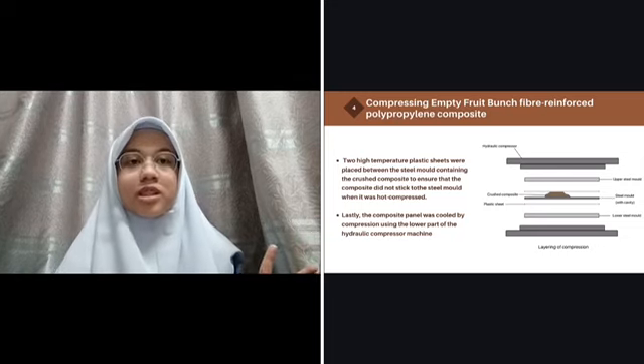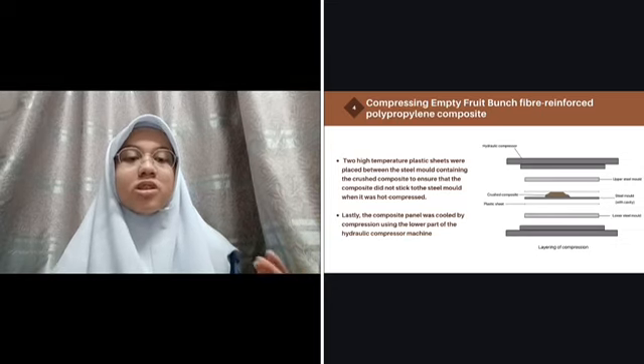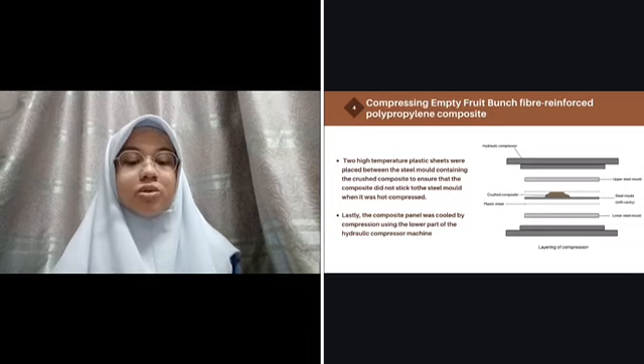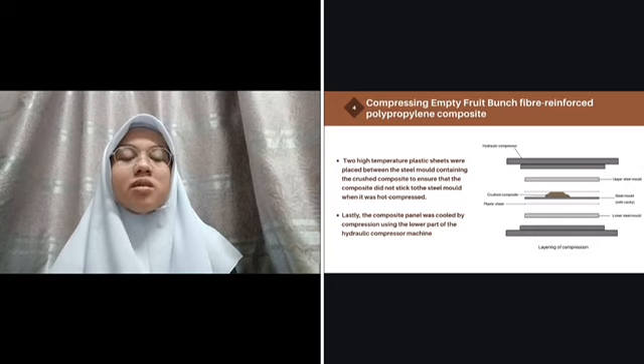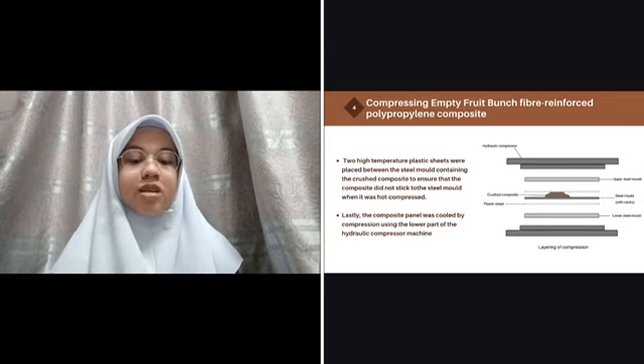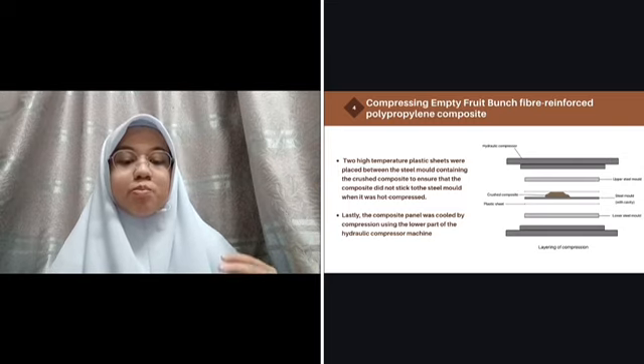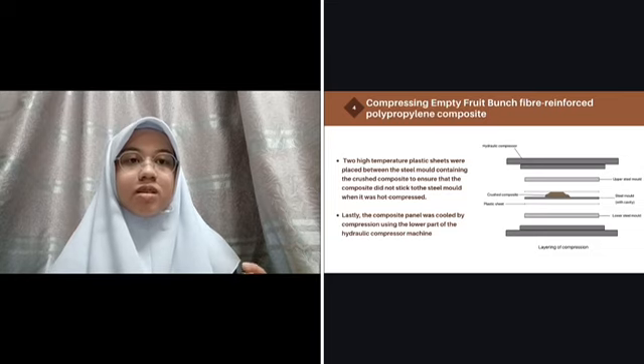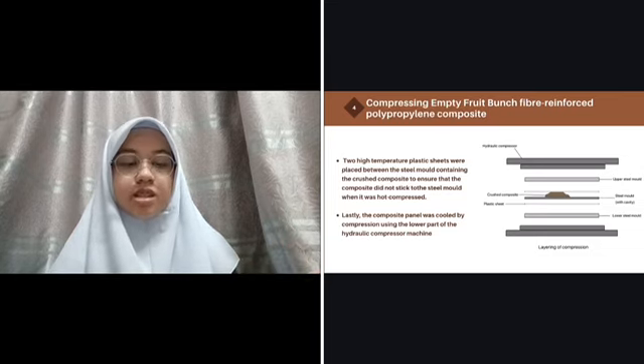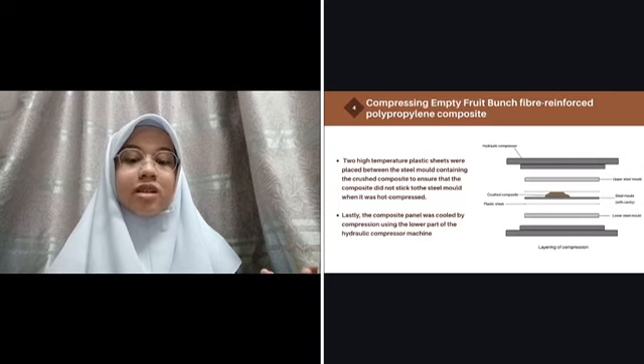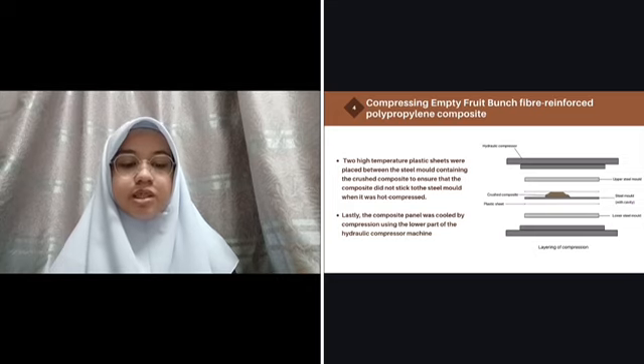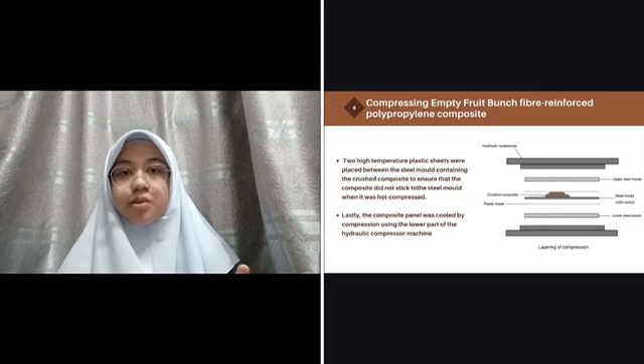We placed two plastic sheets with high temperature resistance between the steel mold that contained the crushed composite to ensure that the composite did not stick to the steel mold when it was hot compressed. The picture on the right shows the arrangement of the layering of the compression. As you can see, the plastic sheet was put in between the crushed composite to ensure that the composite does not stick to the mold when it was hot compressed. After we hot compress it for 20 minutes, we cool it down using the lower part of the hydraulic hot compressor machine. And that's how we obtain our final composite panel.